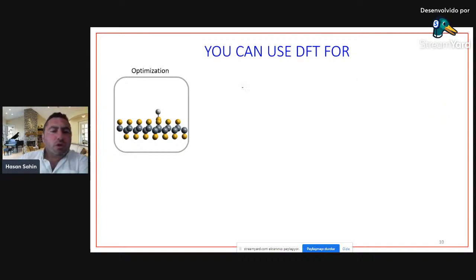Okay, and look at this atom. It's a transition metal atom approaching towards the surface of fluorinated graphene. Yellow atoms are fluorine atoms. As you see here, the transition metal atom removed one of the fluorine atoms from the surface. It's a simple structural optimization calculation. And as you see, the transition metal atom is removing the second fluorine atom from the surface. So this structural optimization calculation tells us that if a transition metal atom, titanium in this case, approaches the surface of fluorinated graphene, it will remove two of the fluorine atoms, and those fluorine atoms will be bonded to titanium.